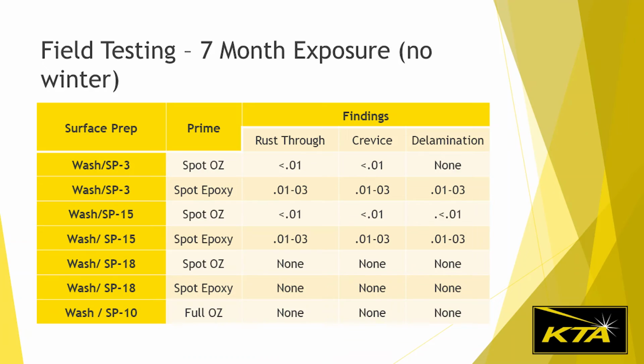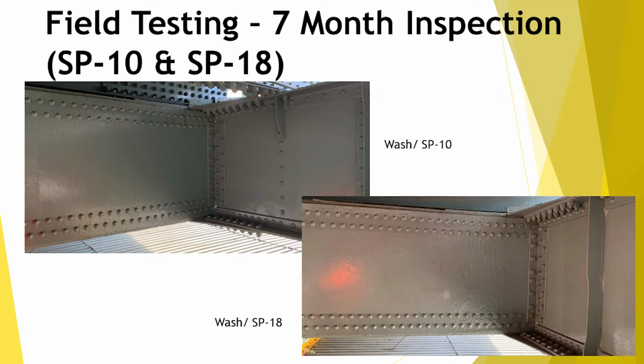These systems were also evaluated per ASTM D610 after 7 months, and it did not include a winter exposure. The spot organic zinc systems with SP3 and SP15 were performing slightly better than the spot epoxy systems with the same level of surface prep. As you would expect to see, SP18 and SP10 are showing no signs of corrosion after the 7 month evaluation. Here are just a couple of photos, SP10s on the top, SP18s on the bottom.